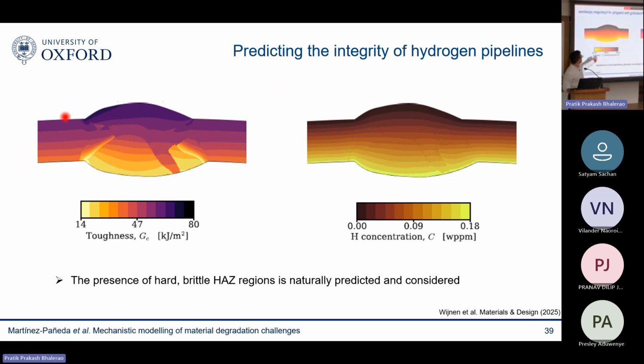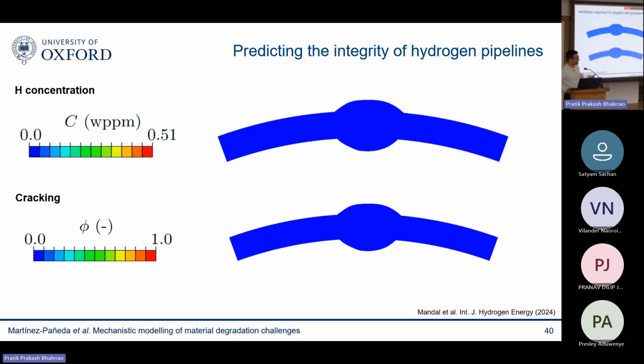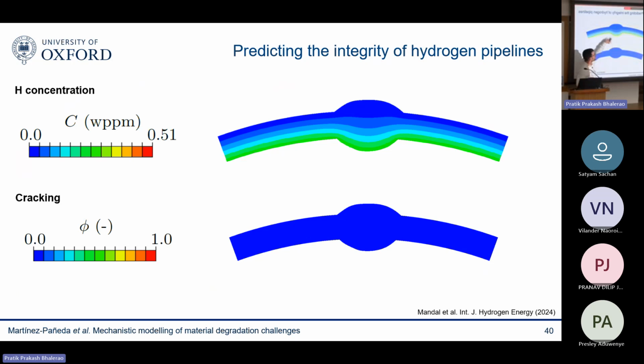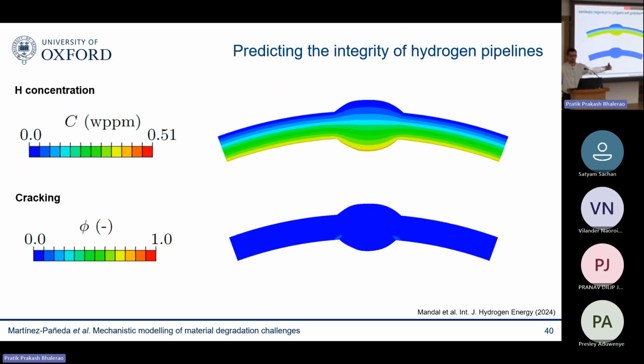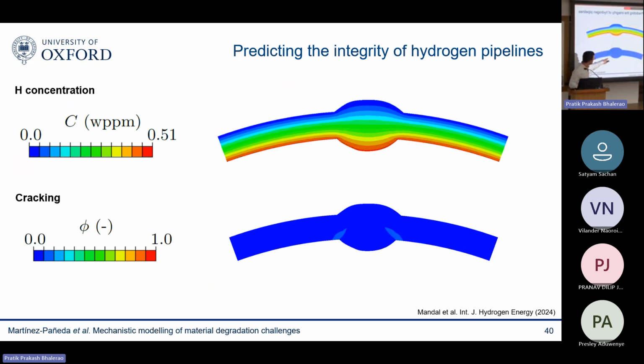And then we can model, of course, the hydrogen concentration, and then you start increasing your pressure. That leads to an increased hydrogen concentration. The hydrogen starts diffusing through the weld, and then eventually at some point you will see that a crack appears here. So we can start ramping up the pressure slowly, and then eventually we know when the pipeline is going to fail. So then we can do that as many times as we wish, changing the welding process, changing the defects, changing the materials, changing the hydrogen conditions, the purity, the pressures, and so on.